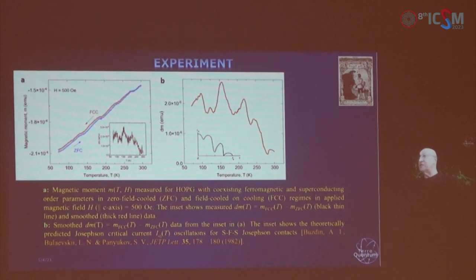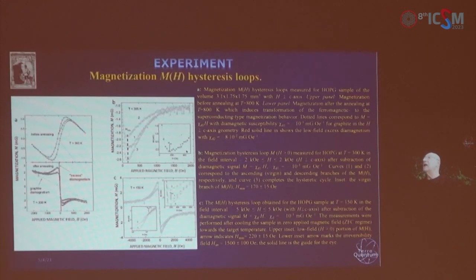And this is another beautiful experimental observation: the oscillations of the difference between the zero-field-cooled and field-cooled magnetizations, which exactly follow the theoretical descriptions obtained for these superconductor-ferromagnet-superconductor Josephson junctions. And this is the final thing, the hysteretic loops, which have been observed in this sample. This immediately gives us the estimate that this superconductivity is indeed related to wrinkles, because only a small part of the volume becomes superconducting.